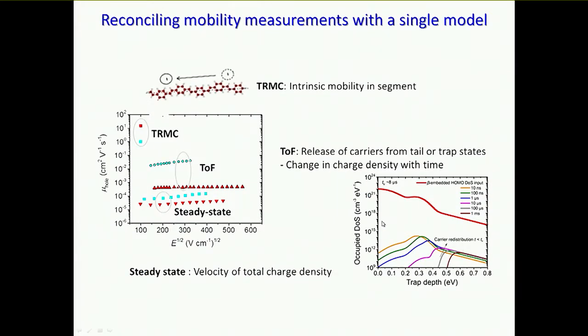And so if we look inside that and see what's going on, we can consider first the simplest measurement of all, the transient microwave conductivity, not our measurements but others. Here you're just probing conductivity within a segment. And when you have the beta phase segment, it's more planar, it would be more strongly coupled, so the mobility is going to be higher. That makes sense. And then when we get to time of flight, what we found was that our photocurrent mobility measurement was not probing so much the average velocity of charge carriers through the film, but the rate of release of charge carriers from these traps. And if we look at what's happening to the charge carrier population as time advances, we could see that the strong feature that we interpreted as a transit time was really a release from traps time.